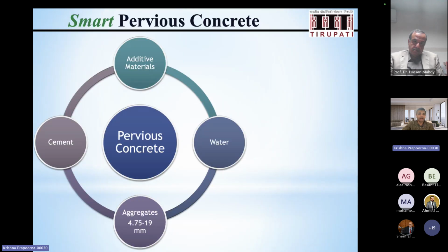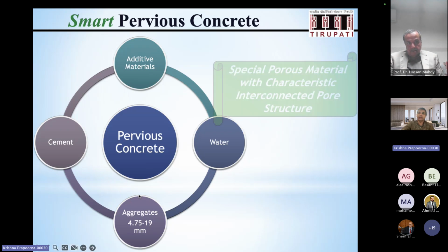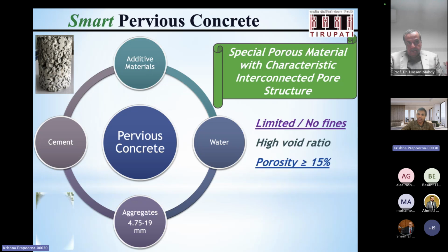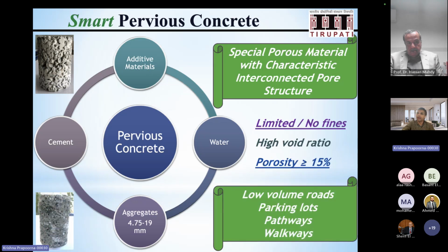So what is pervious concrete? In a nutshell, it is simply a regular concrete, except that you have very little amount of fine aggregates or no fines at all, absolutely no fines. Very high void ratio, very high porosity, about 15 to 20%, maybe 40% sometimes. Same cement that you use, water and aggregates.